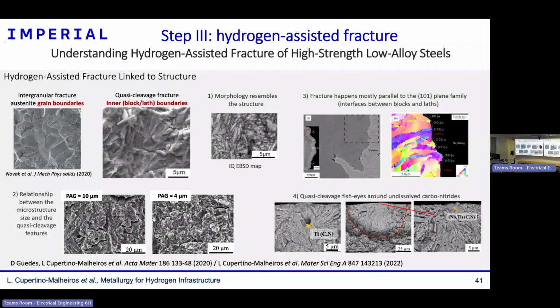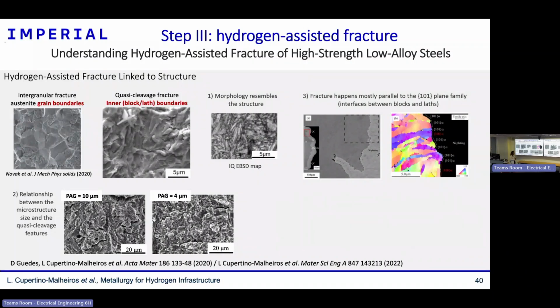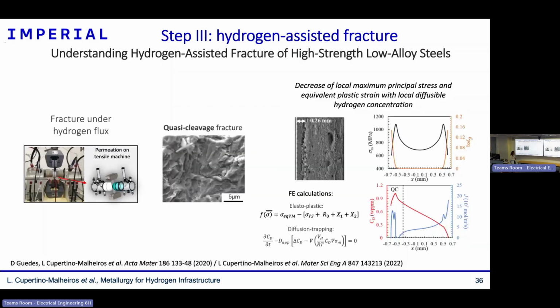It's not possible to say that it's only that. When I was establishing some local fracture criteria, using modeling to see what are the stresses and the plastic strain necessary for fracture, it seems also that plasticity can help. So overall, for these steels and in agreement with the literature, we say that we have a combined effect of plasticity and decohesion. For some cases, we see that decohesion is more evident, but it's still debatable, I would say.